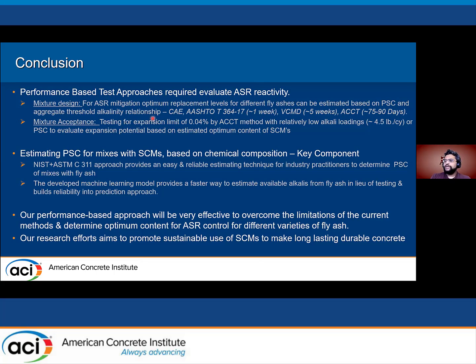So in conclusion, we would like to say that performance-based test approaches are really required to evaluate the ASR reactivity. The first consideration is towards the mixture design. The optimum replacement percentage should be based on the composition and the performance. Once the optimum level of replacement has been determined, the mixture acceptance testing could be performed by the ACCT test method, which usually takes around 75 to 90 days. And it could be performed at the level of pore solution concentration, alkalinity, or low alkali loadings.